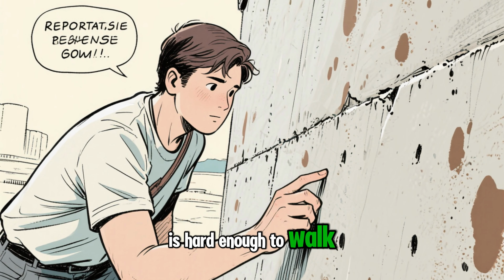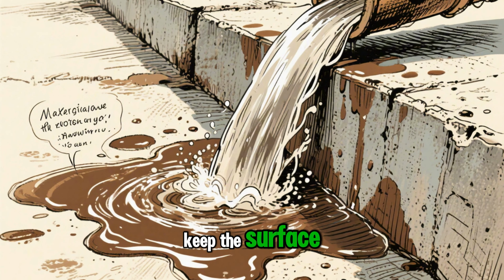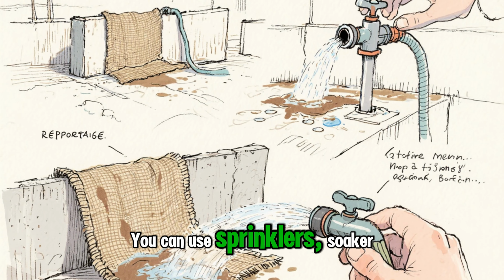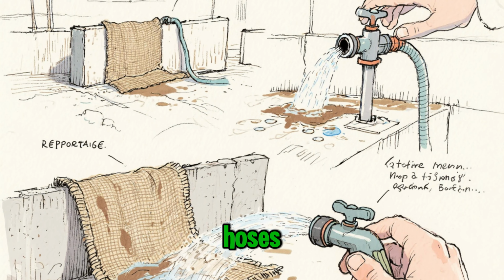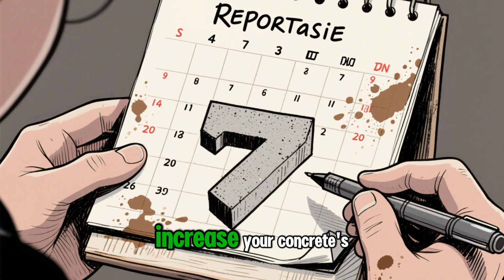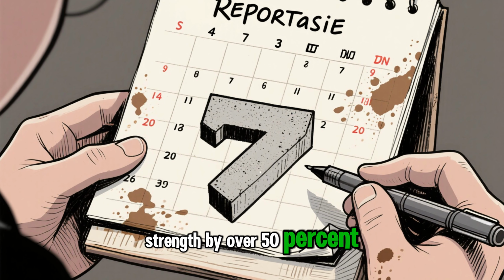And third, proper curing is non-negotiable. As soon as the concrete is hard enough to walk on, you need to start curing. The easiest method is to keep the surface continuously wet. You can use sprinklers, soaker hoses, or cover it with wet burlap or blankets. Do this for at least 7 days. This simple step can increase your concrete strength by over 50%.